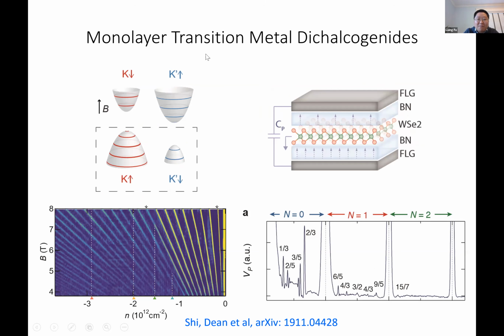And they studied this monolayer transition metal dichalcogenide under a perpendicular magnetic field. And as you can see from these results here, this is a capacitance measurement. And you see all these beautiful Landau levels associated with holes. And a magnetic field also couples to the valley pseudospin. So the valley degeneracy is broken. So we get quantum Hall states at all integer fillings, both even and odd fillings. And moreover, you see this whole sequence of fractional states that shows up. Okay, it's a testament of the amazing material quality that is now available.